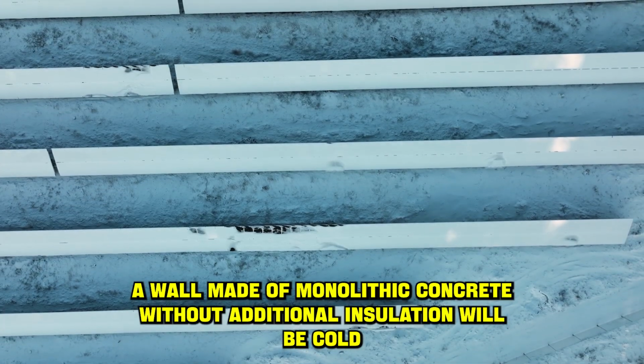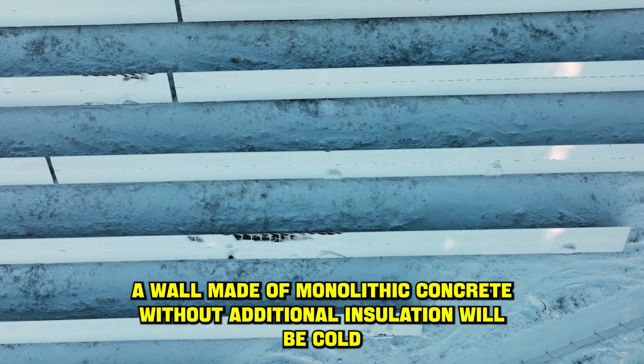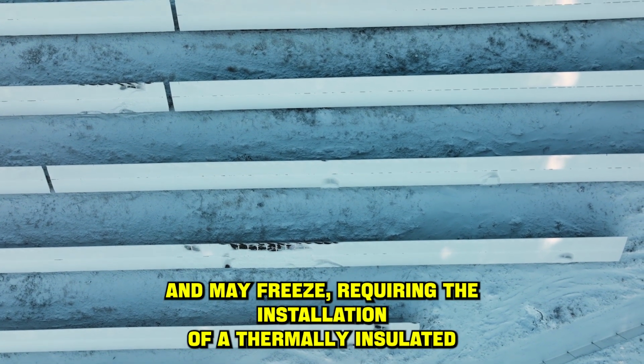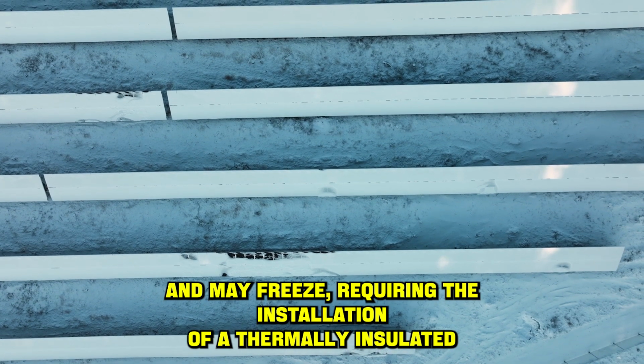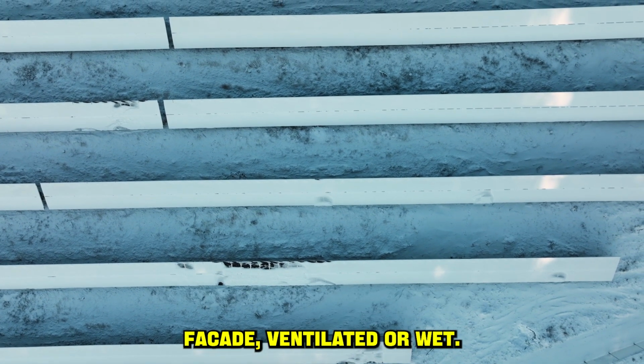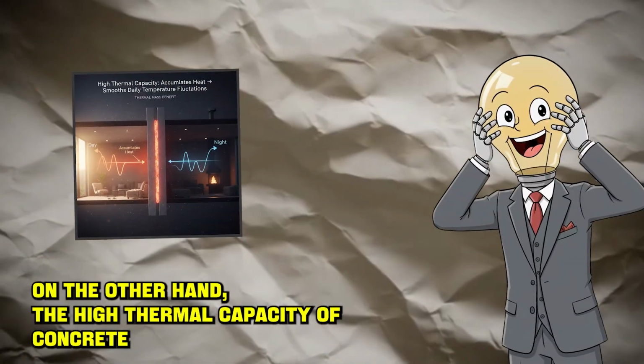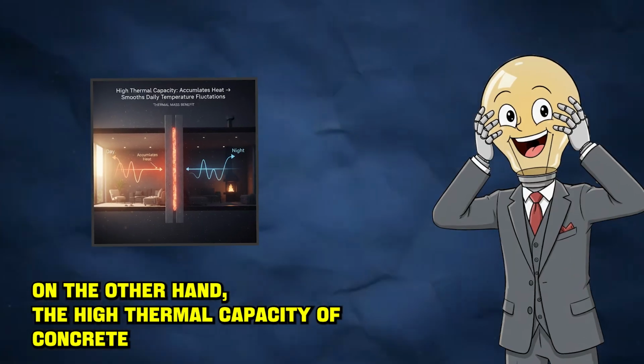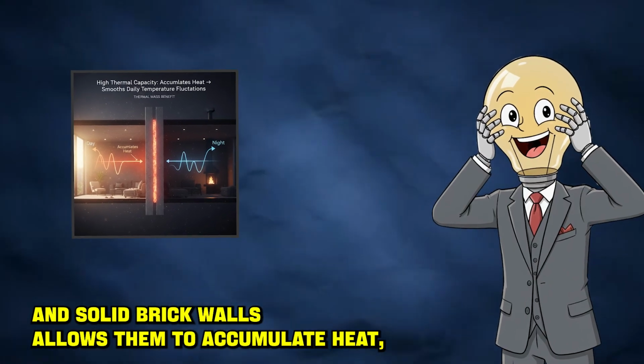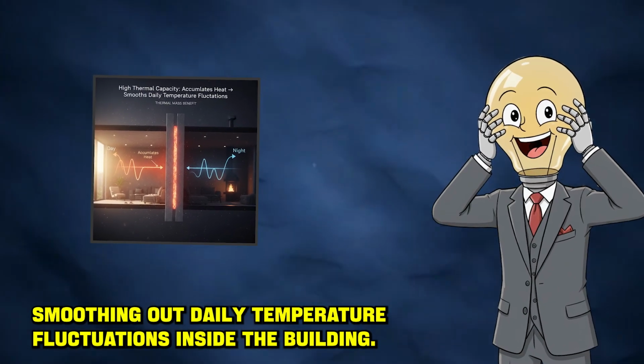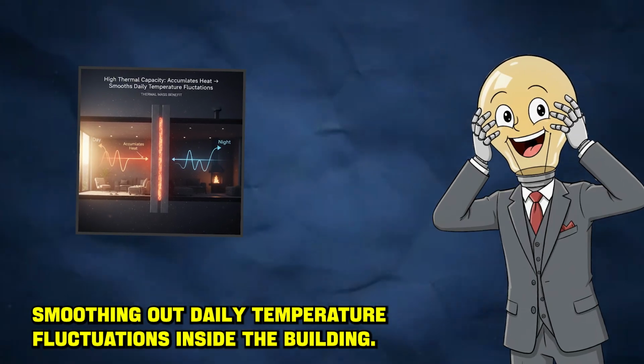A wall made of monolithic concrete without additional insulation will be cold and may freeze, requiring the installation of a thermally insulated facade, ventilated or wet. On the other hand, the high thermal capacity of concrete and solid brick walls allows them to accumulate heat, smoothing out daily temperature fluctuations inside the building.